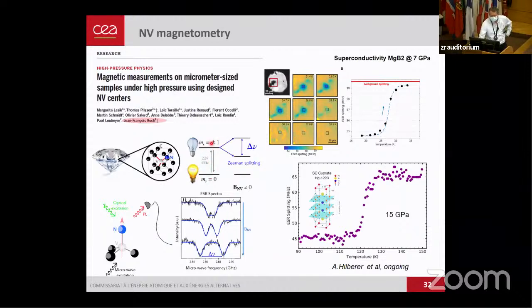And since this level is of the spin 1, it is sensitive to the Zeeman effect, and so it can be split under a magnetic field, and you can detect the magnetic field, or change of magnetic field, over your sample. So it's a very simple optical measurement of magnetism, with spatial resolution, and this has been applied to standard superconductors like MgB2 at 7 GPa, and the work is ongoing at 15 GPa on cuprate. But to go to higher pressures, there are many more properties to disclose and effects to master, and there's a lot of work being done by the Jean-François Roch group to push that in extreme conditions.